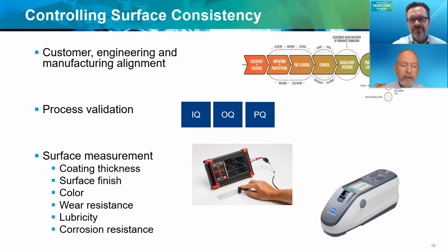What we do with very color sensitive customers is make an agreement on what the maximum color shift can be. The human eye can start seeing about a 3 delta shift, and what we see is our customers are usually looking for a little bit less than the 3 delta shift. So you can't even physically see this, even if you have a good eye for color. That's where the spectrophotometer is critical.